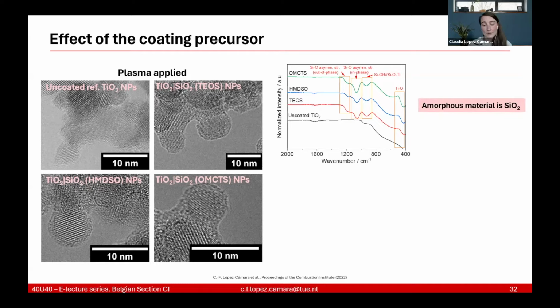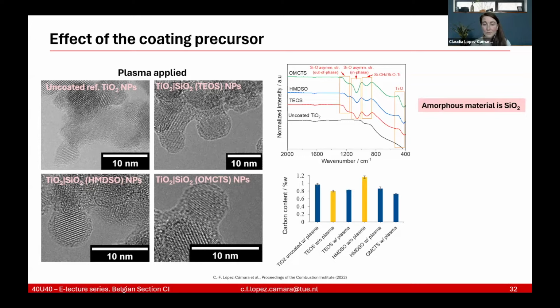Another thing that can happen when you have a flame is that you have hydrocarbons incorporated in your material, because we do have hydrocarbons in the flame. Because of that, we checked the content of elemental carbon, and we see that the content of carbon in all our samples was below 1.2%, which is basically negligible. So there was no hydrocarbon incorporation in any of the samples, which was really good. And then after getting the BET analysis on the surface area of these samples, we saw some numbers that we did not know how to explain.